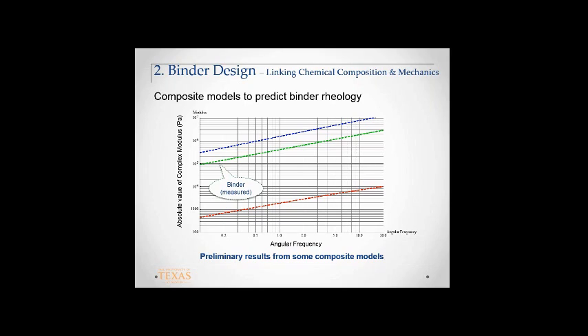So this is the binder master curve. Again, you have complex modulus versus angular frequency. You have the stiffness of the binder here that is measured, so that's experimental. You have asphaltene. This is also experimental, so this is an asphaltene doped binder. And we have a petrolene doped binder. So when I say petrolene doped binder, I mean that the binder has all the other three fractions. So other than asphaltene, all other three fractions are doped into this. So I have this on one end, that on another end, and this is the measured binder properties.